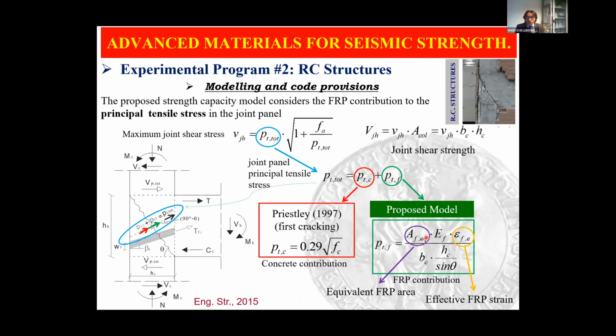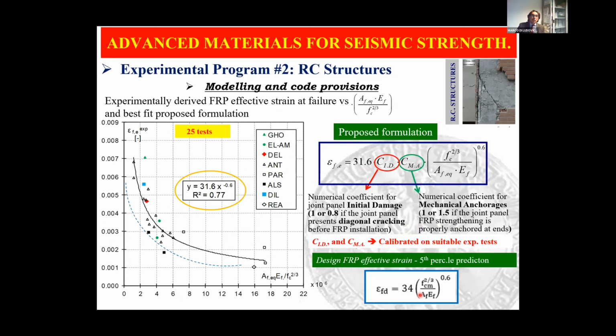And the idea is to compute the FRP contribution as the product between the area of FRP in this direction, so the equivalent FRP area, times the stress in the FRP, which is given by the Young modulus times the strain. And the very important thing is to calibrate how much is the effective FRP strain. To do that, we collected data on several tests along with our tests, on beam column joints strengthened by using FRP, and when FRP failed. And what we did was to find a correlation between the effective strain and a parameter which is given by the area of fibers, the equivalent area, the Young modulus of fibers, and the concrete compressive strength.